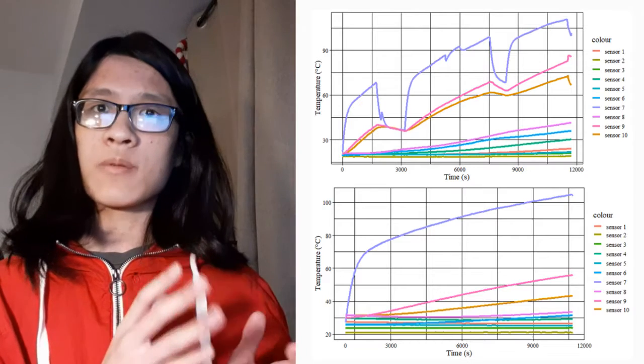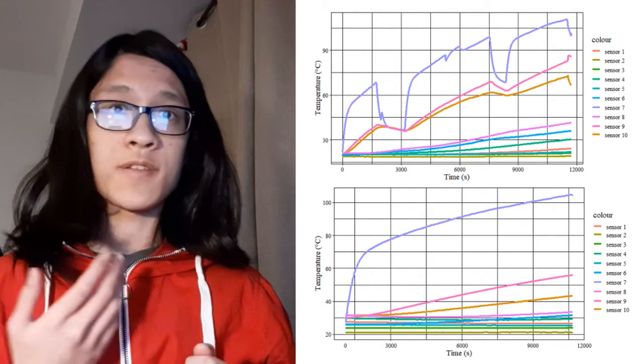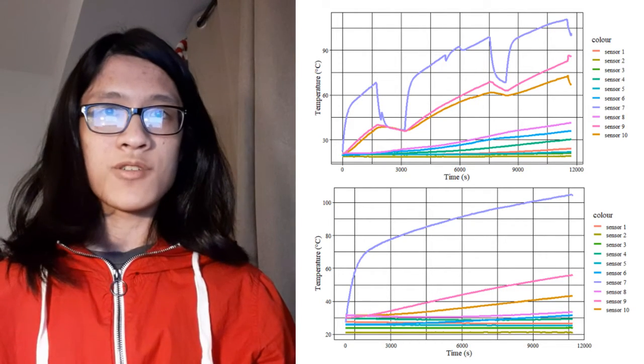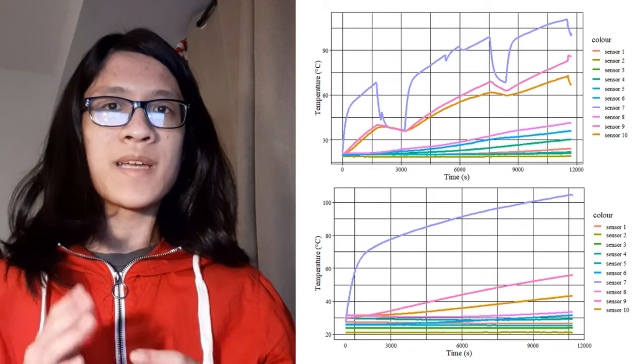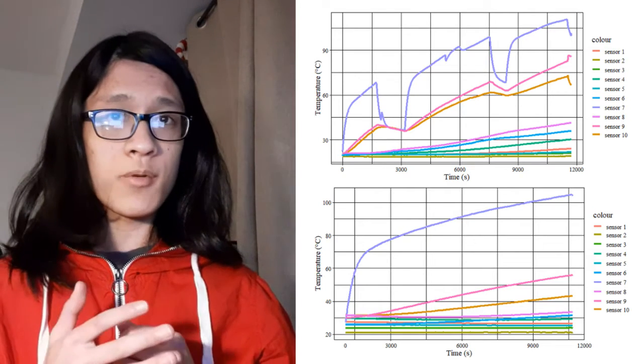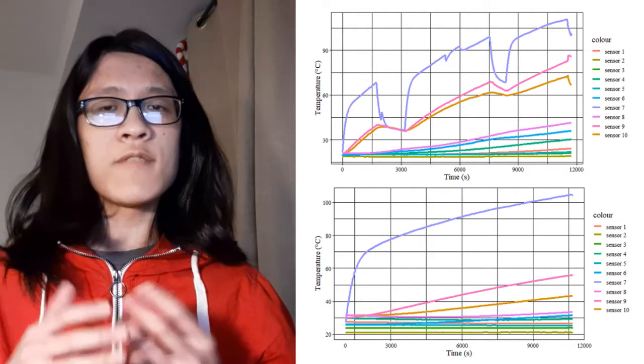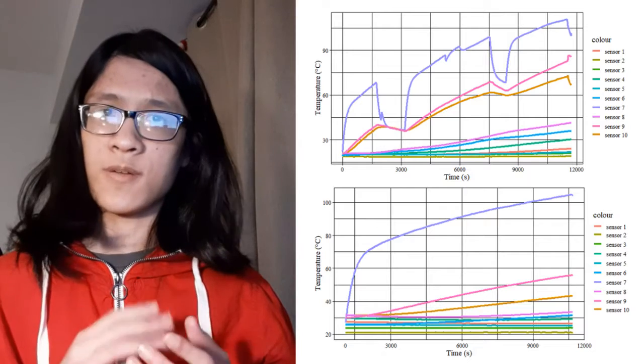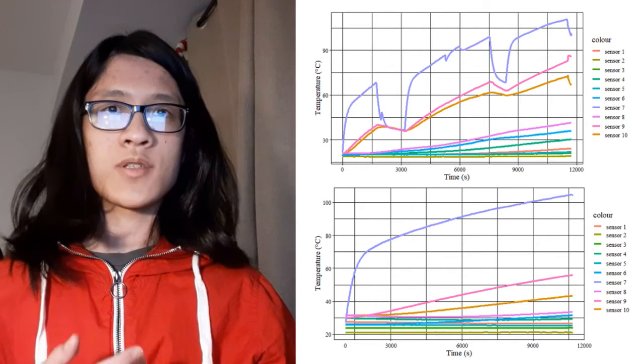These graphs describe the recorded temperatures over time for each of the two experiments. Over time, the temperatures on all parts of the system increased from the baseline ambient temperature levels until the point of stabilization, when all the various heat fluxes in the system became equal to each other, as indicated by the final temperatures in the graphs.